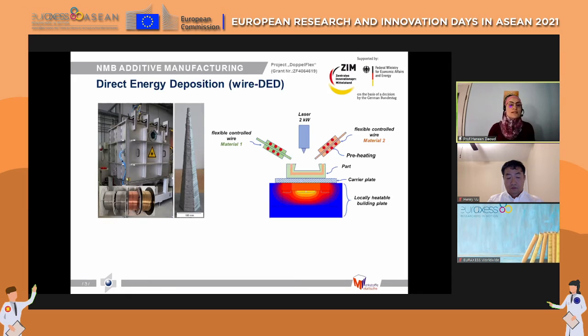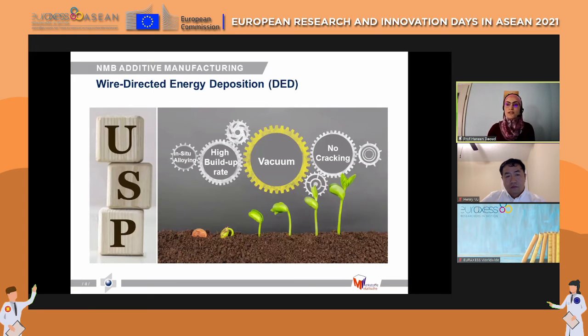Our self-developed directed energy deposition focuses on the use of two wires. Here you can use the same or different types of materials combined with a high laser power, for example, 2 kilowatts. We have also different functions like the preheating of the wires and the preheating of the carrier plate. The question is why we consider that our process is different and even better than the commercially available processes. The first reason is that our process is worldwide the only process carried out under vacuum. This means that the oxygen level will always be very small. The second point, as a result of the preheating of the wires combined with the preheating of the carrier plate, is that you will not have any crack formation when printing different metallic components.